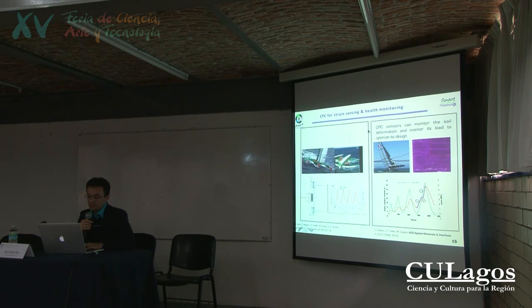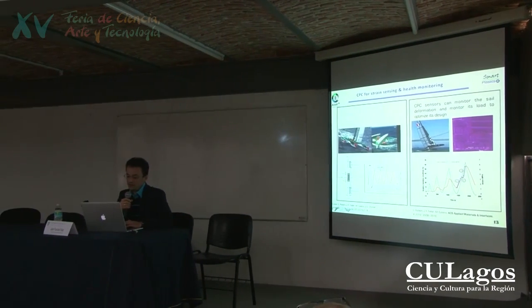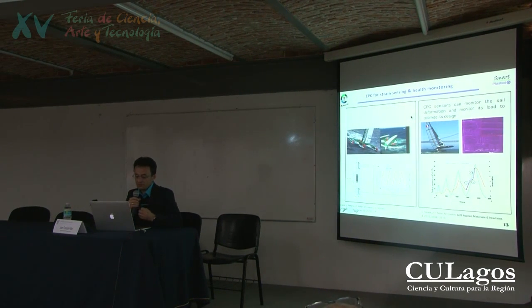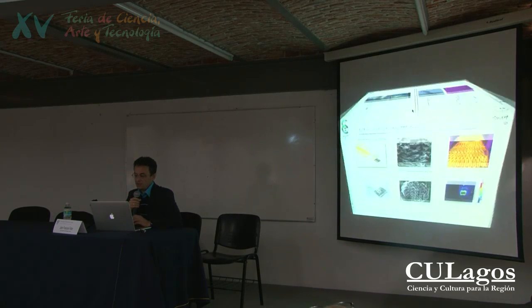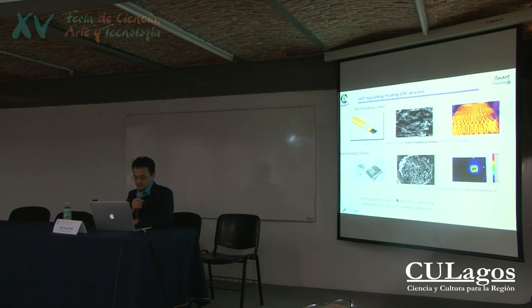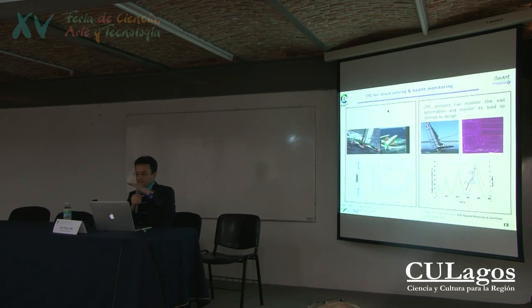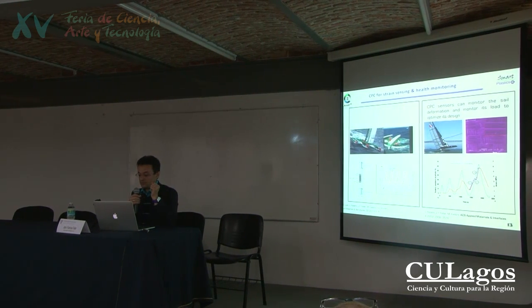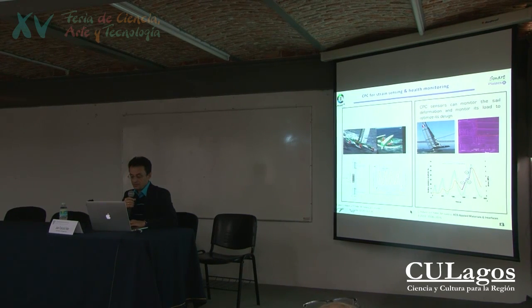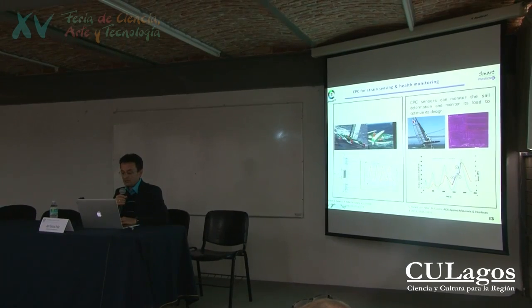And the materials, of course, are submitted to enormous solicitations, to waves, to wind, and so on. So quite often they are broken, even if they are made of the strongest materials known for this kind of application, that is to say carbon fibers with epoxy polymer. Even in this case, they can break. So it can be interesting to anticipate the breakage by the introduction of sensors inside the composite. So you will measure the resistivity of the composite, and if it is going to break, you can trigger a signal of alarm to prevent the complete destruction of the composite. So you can do this on composites, and you can do this also on sails.